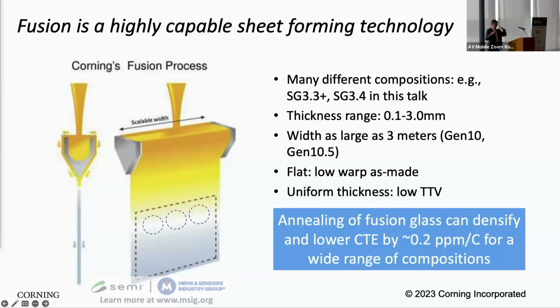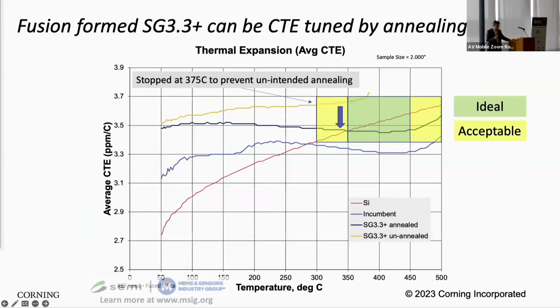If you heat the glass up to the annealing point for an hour or two, you actually densify the glass, and the CTE can be dropped by a certain amount. So if the glass as drawn from this process isn't a perfect match to silicon, we can add an annealing step and make the CTE match perfectly.